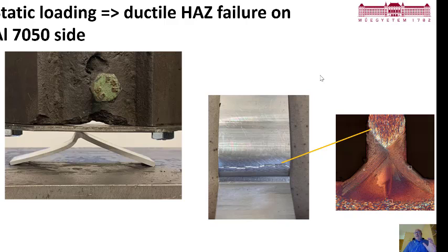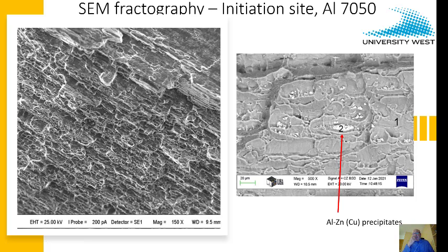And we continued this evaluation by forcing this weld to break. I'll show you some regular tests. This is kind of non-traditional testing. We wanted to see whether we can break the weld in the heat affected zone. And we were able to actually bend it and break it right there, very close to the heat affected zone, and found that, lo and behold, coarsened grain. So this seems to be the weakest area, yet you will see from the regular testing that this so-called weakness is only about 15% of the strength of the base metal from static testing. Very good joint efficiency. Started 85-90%, and you will see later that we reached almost 95% joint efficiency.